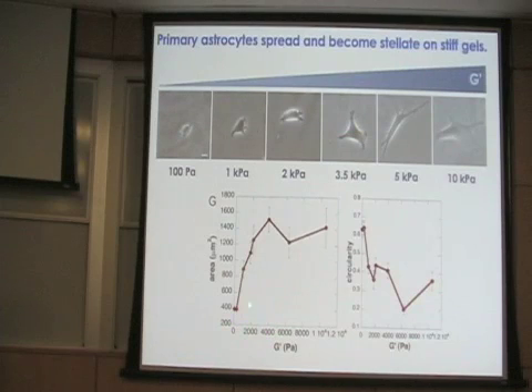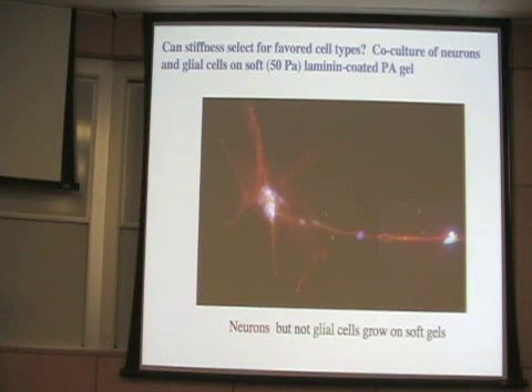So one of the things we did a few years ago was to take this quantitative information, look at the range of stiffness where things like astrocytes get activated, which is something you don't want to do in a central nervous system injury site, and see if we can find materials that are soft enough so they're promoting of neuron growth, but not very excitatory for glial cells like astrocytes. And in fact, you can find materials like this. So here's an example of taking a whole explant of the brain cortex of a mouse, so all the cell types in the brain, and plop that down onto a culture dish that has either a very soft gel or, as I'll show you later, a stiff gel on it, and then go away for 3 or 4 days and come back.